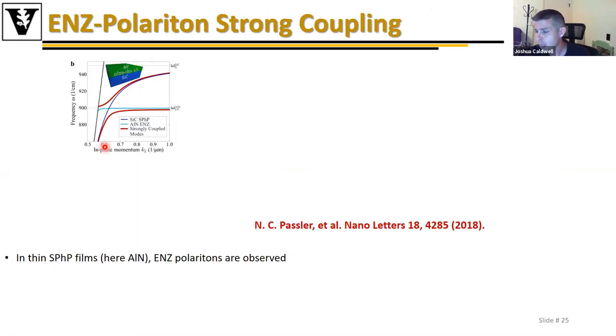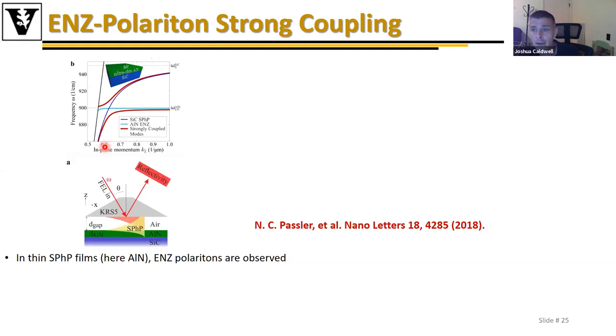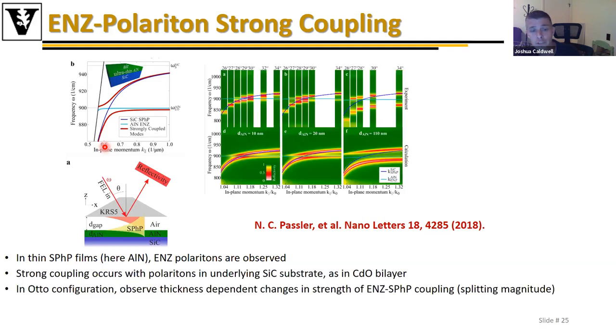Now, we were also able to demonstrate this within phonon polariton systems. Shown here is an ENZ layer of a thin aluminum nitride layer on a phonon polariton layer of silicon carbide. In collaboration with Alex Parman's group, and Simone, we were able to demonstrate the overall dispersion of these modes in the Otto configuration.